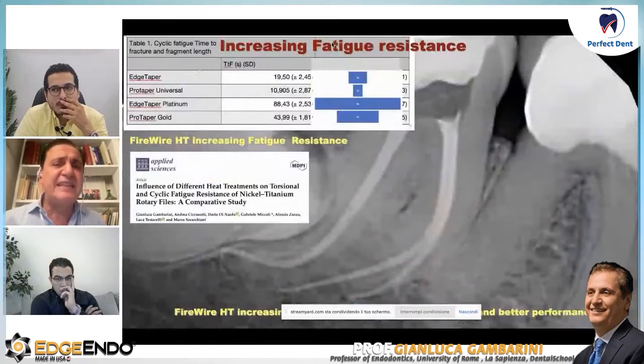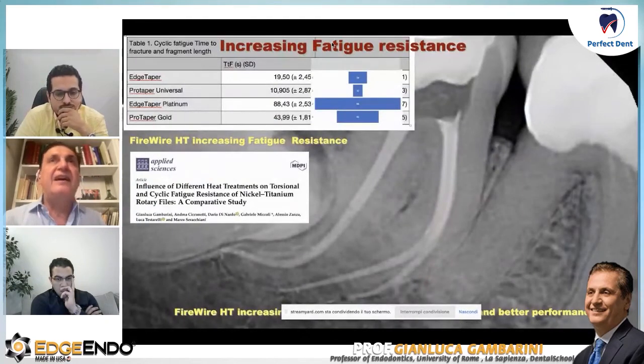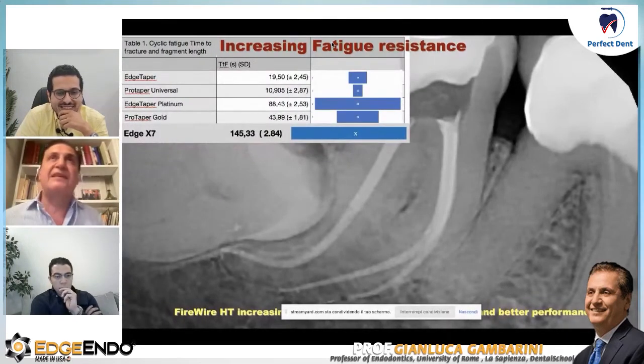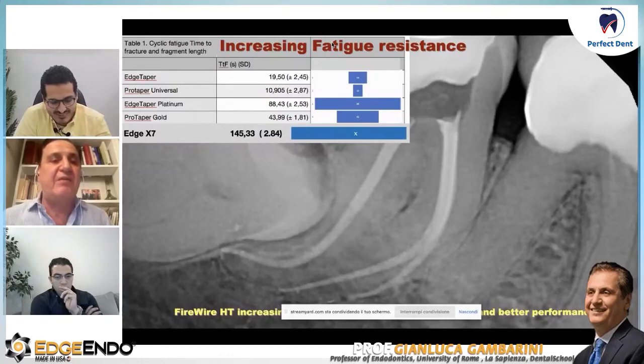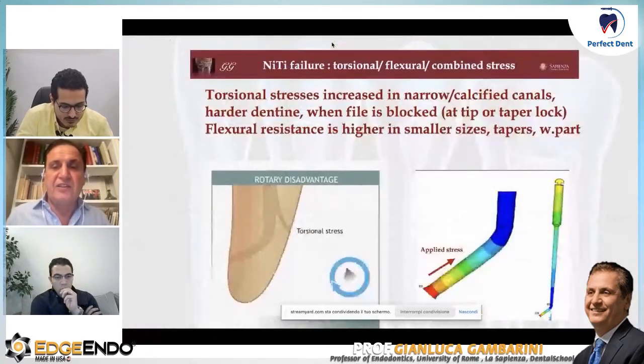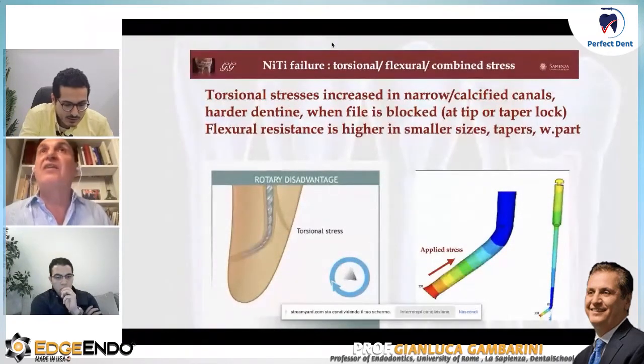So practically speaking, what happens is that all this heat treatment, especially for the X7, also increases fatigue resistance, the resistance of the file inside of the curvature. So let's say that the heat treatment, the FireWire treatment, makes our instrument much more suitable than any other files in a curvature like this. And if we want to once again show the data that we made in our research and published, we see that EdgeEndo is not only the most flexible, but is also the most resistant to cyclic fatigue or to flexural stress. So this is quite interesting, but we have to be very honest when we speak about files.